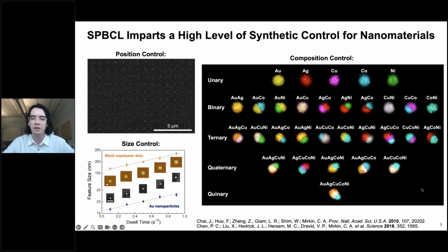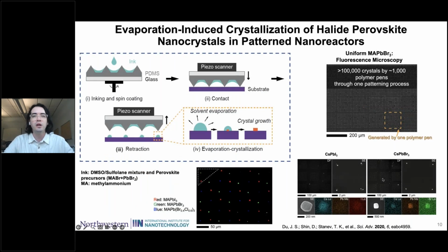by other synthetic means. And so we've expanded this type of nanoreactor synthesis to other types of materials, but all taking advantage of this very small volume confinement method. So in this case, we're making halide perovskite nanocrystals, where we do the same idea of putting inks onto the pen tip, so just these molecule precursors, patterning them on the surface. And in this case, the nanoreactor is, instead of a polymer, a volatile solvent. So over just a couple of minutes, it'll evaporate. And as it evaporates, the perovskite precursors will crystallize into single crystals.